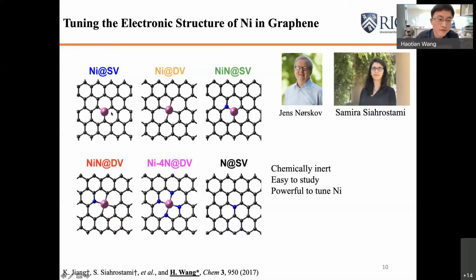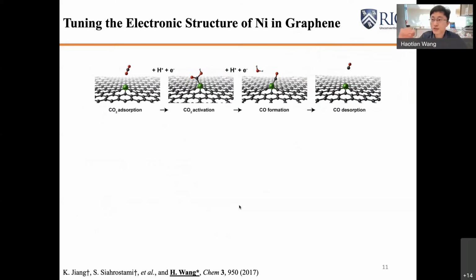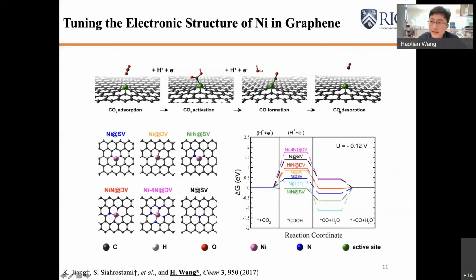makes sense. So we tested the nickel single atoms, we doped the nickel single atoms in the graphene defects, different types of defects, and we tried to tune different coordination, like a 1 nitrogen coordination, 4 nitrogen coordination, and so on. And we tried to simulate each of the elementary steps, starting from CO2 adsorption, CO2 activation, CO formation, and CO desorption. As we can see from this thermodynamic free energy chart, if we look at the nickel metal first, the CO2 activation step is relatively easy on the nickel surface. But once the CO is formed on the surface, the desorption becomes very difficult. As you can see, this thermodynamic sink binds the CO strongly. So that agrees well with our previous prediction.